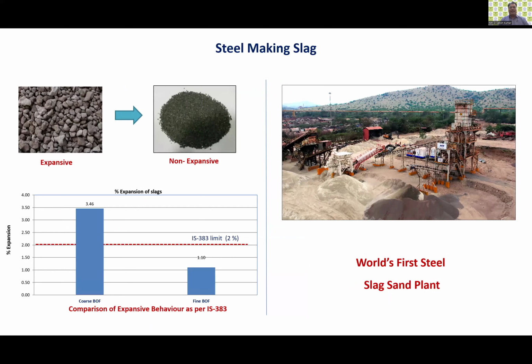What we have done at our place is we try to crush them very fine, and we find that the expansion behavior, which if it has to be used as a coarse aggregate, where we need to do a lot of aging steps to be involved to convert them into product. We crush them and make it very fine, where its expansion behavior significantly reduces, because the free lime and the free MgO which is present in it, which are expansive in nature, when they come in contact with water, gets removed.